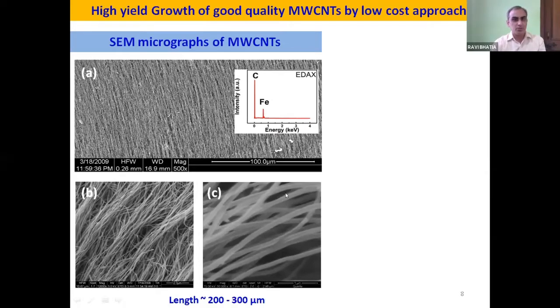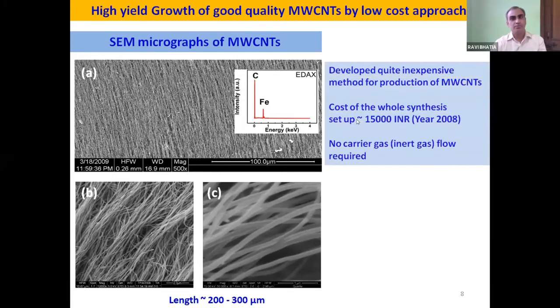Figures B and C show very nicely oriented carbon nanotubes. However, when we carried out an EDAX, we found that there is iron present in the carbon nanotube, which cannot be seen in these SEM micrographs. So I was talking about the cost effectiveness of this particular technique, that we developed a setup having the capability of producing multi-wall carbon nanotube of this level with no carrier gas at all.